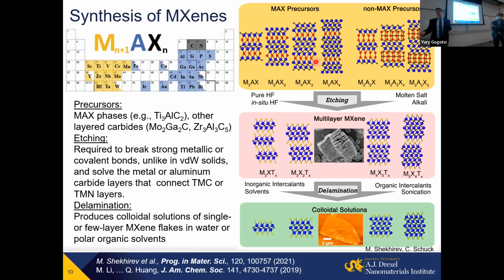So what we decided to do was use an approach that I've been using for a long time, selective etching, to open channels for lithium to go in and etch it. And Michael Naguib, the student who was working on this project, he's a professor at Tulane University now, by the way. He tried titanium silicon carbide and again failed.